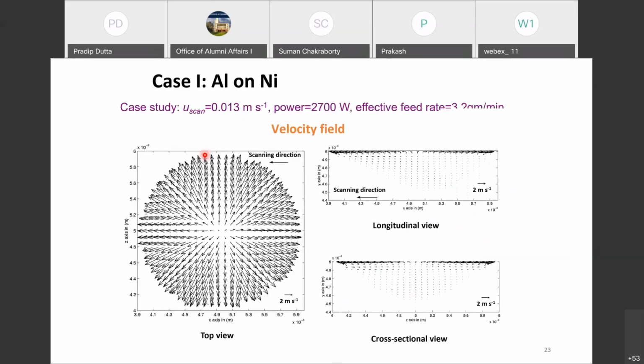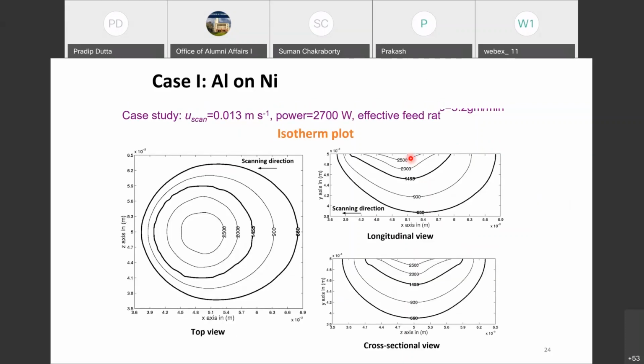Now we turn to our model and we produce a weld pool. These are the top view, the side view and the cross-sectional view. We look at the weld pool, and this is the depth of the pool, and there is very high Marangoni convection on the top surface. Then we look at the temperature plots as we see here. These dark lines are the melting points, this is the pure aluminum and this is that of the pure metal, nickel, as we see here, right? So that would define our weld pool.